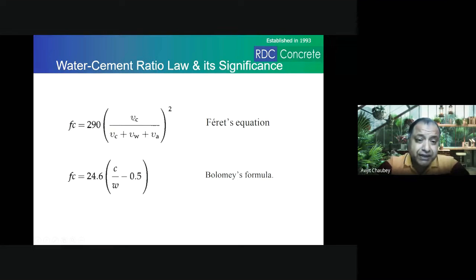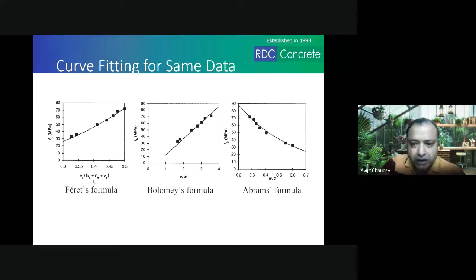So this is Féret's equation, where VC is the volume of cement, VW is the volume of water, and VA is the volume of air. This was the equation that Féret gave. Similarly, Bolomey gave this equation where cement divided by W, cement is the weight of cement, W is the weight of water. And these factors had to be calibrated based on whatever material he had. And then Francois de Larrard, a French engineer again, who's still alive, did around a couple of trials with different cement ratios.